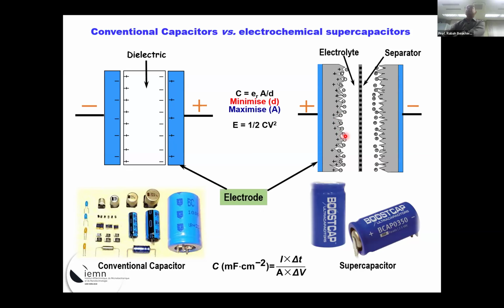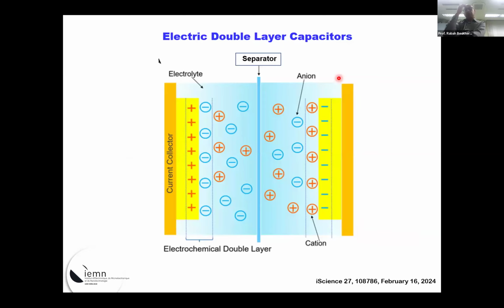So this is really important when you design a material specifically for supercapacitors: you control the pore size in a way that you will accommodate the electrolyte, and that gives much higher efficiency. Otherwise, that's problematic.